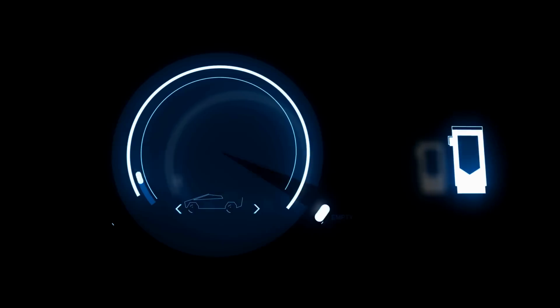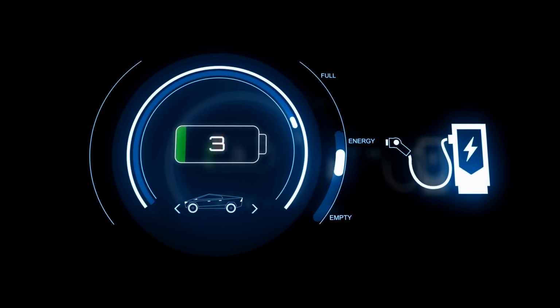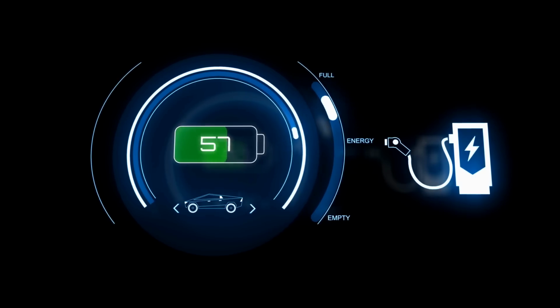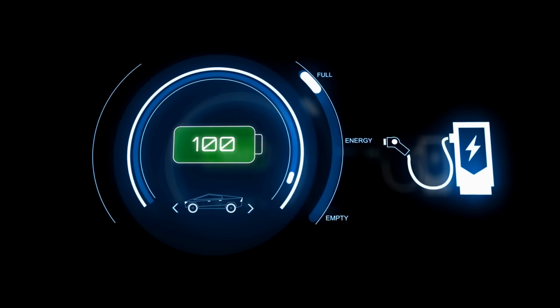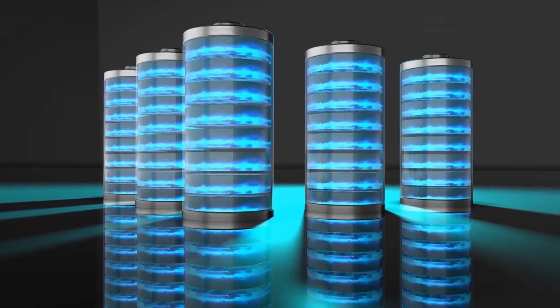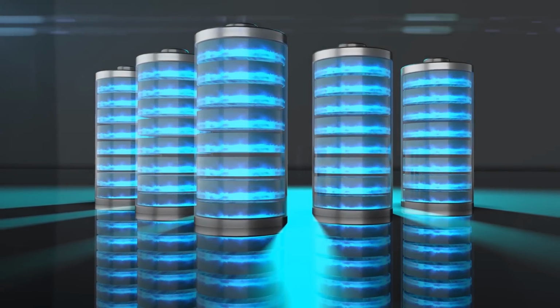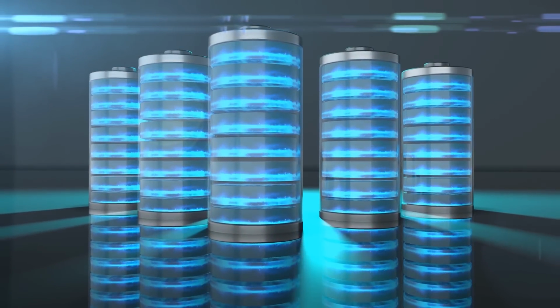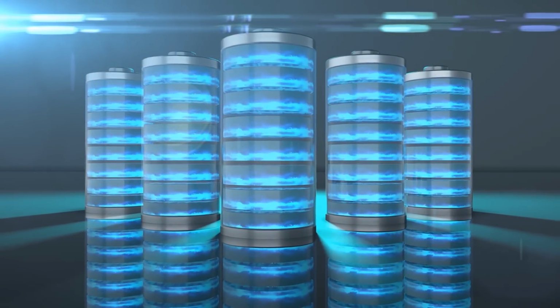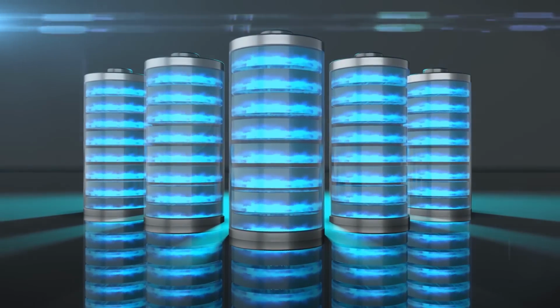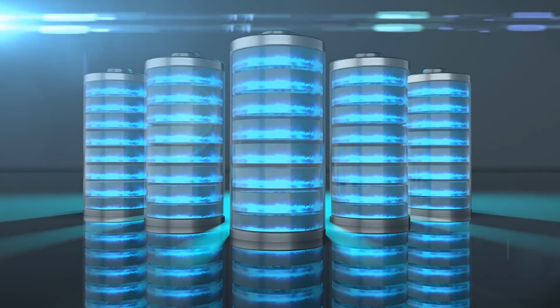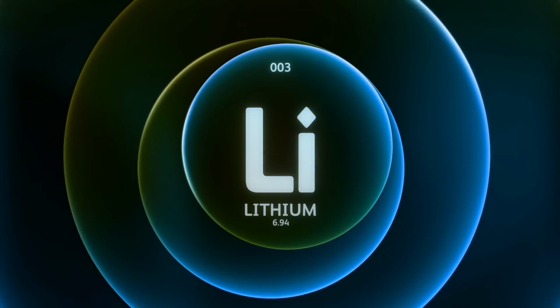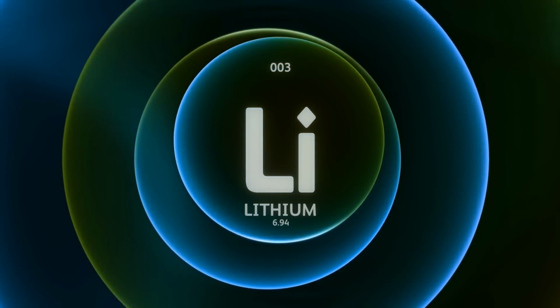In a test like this, I'm assuming that that rate is constant through the whole time. And so you're actually really abusing that battery. Typically speaking, when it comes to charging an electric vehicle, the battery management system is going to limit the charge rate to keep that battery from overcharging and causing problems like lithium plating. And what happens when charging, if you try to charge at too high of a kilowatt rate, you actually have lithium that tries to move too quickly into the anode material. And if it can't actually intercalate into that material, it starts plating on the surface of the anode, which means you actually lose lithium ions in that battery and thus lose battery capacity.